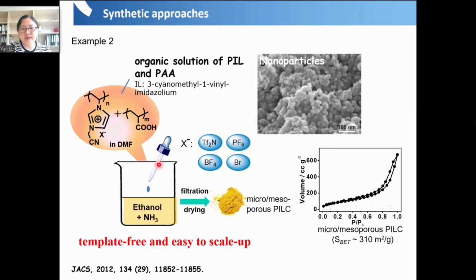and then do the treatment in ethanol with ammonia, and then by drying you will get a kind of meso and microporous poly(ionic liquid) nanoparticles. And from the BET, which is the nitrogen adsorption-desorption method, they show the typical curve of a meso and microporous material, and the specific area can be around 310 square meters per gram.